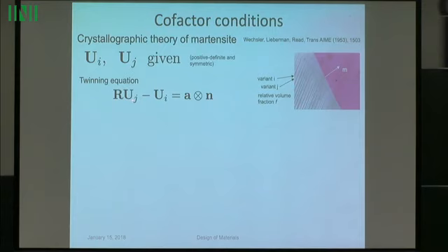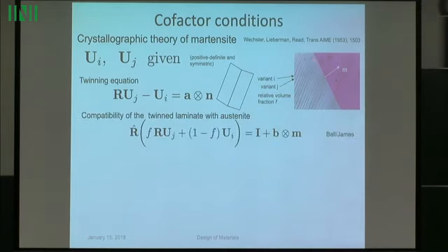So I already described the solution for these bands. You solve this twinning equation. I described reducing the energy in this transition layer to 0 by refining the twins. That gives rise to a second equation, which I didn't write down. That's the compatibility condition that allows you to drive the energy to 0. And this is also the equation you would get in a similar way if you use the branching construction as well. So it's in both cases.